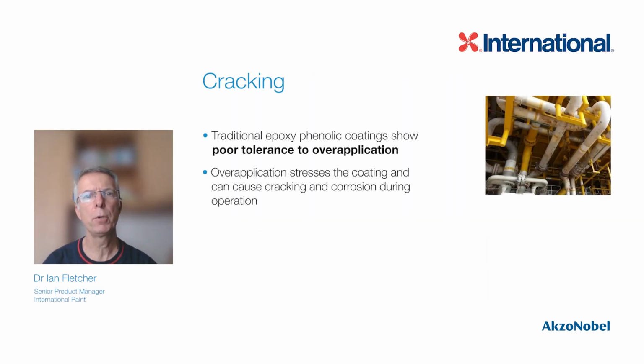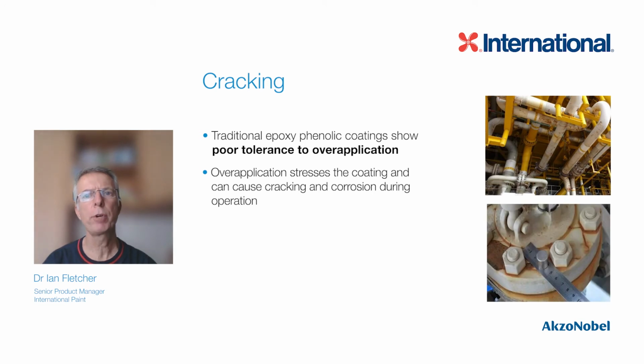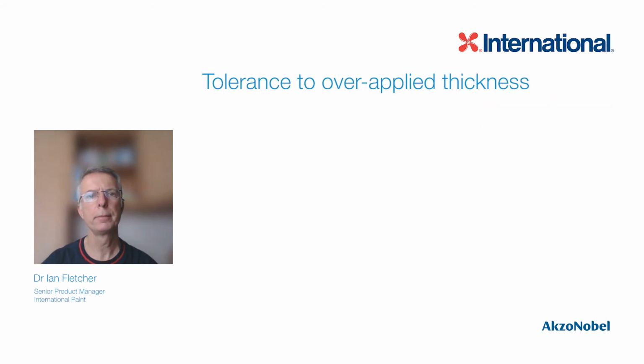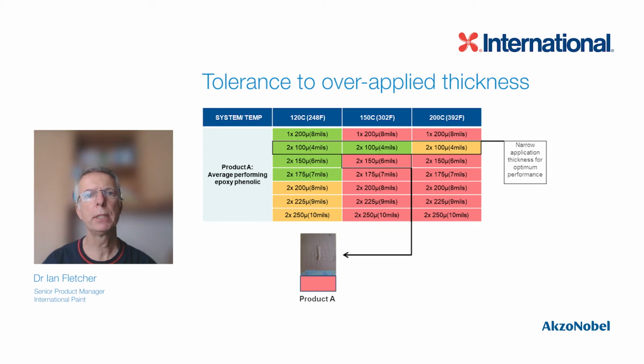Another feature of typical epoxy phenolic coatings is poor crack resistance. Epoxy phenolics show poor tolerance to over-application, and it is common to see cracked epoxy phenolic coatings and corrosion occurring during operation. We carried out a detailed study of over-application tolerance. First, we looked at traditional epoxy phenolics. The results were categorized in 3 ways. Green was for panels that showed no sign of any cracking. Orange, there was some cracking around a weld, and red, there was cracking across the face of the panel.